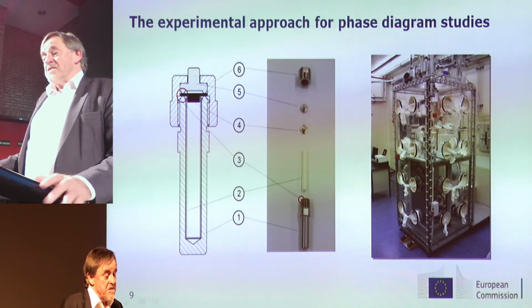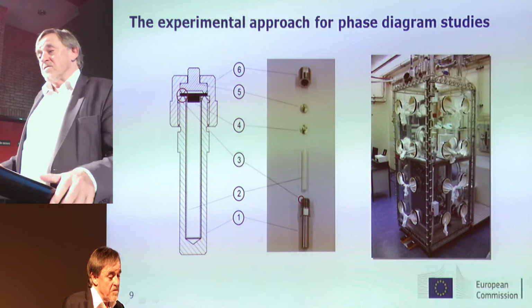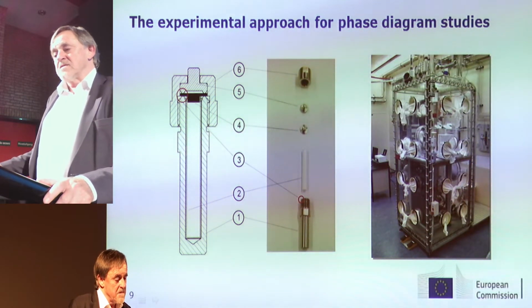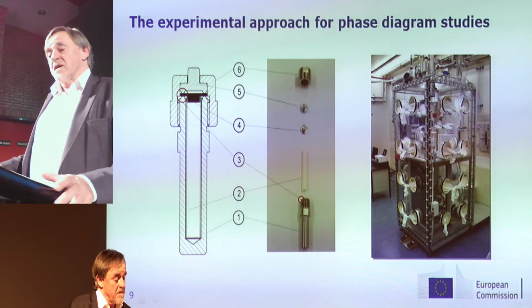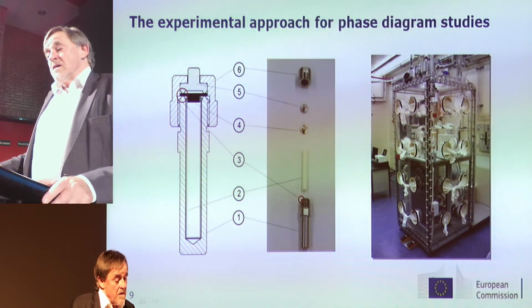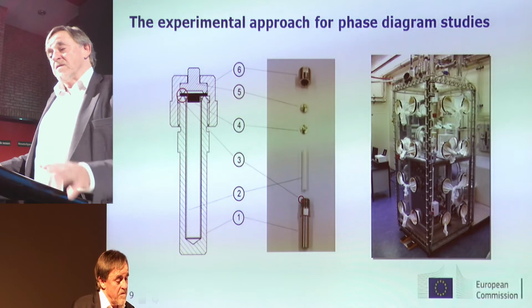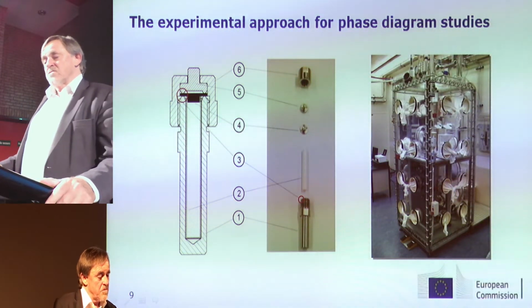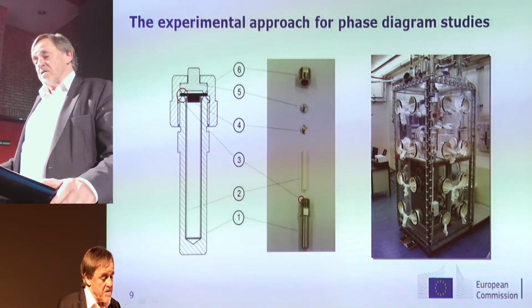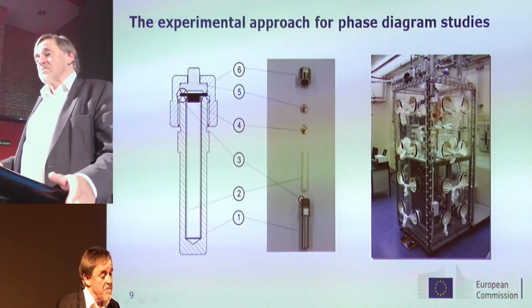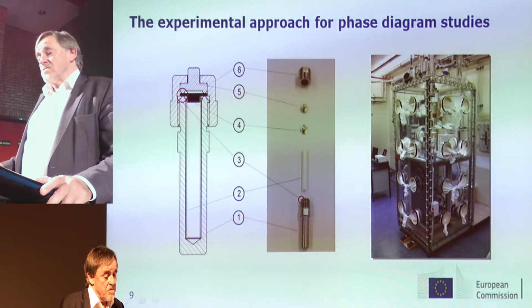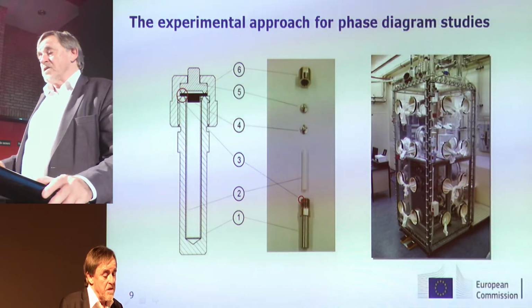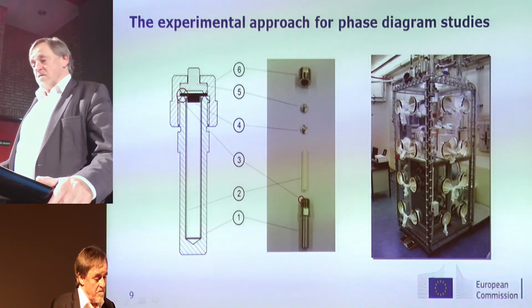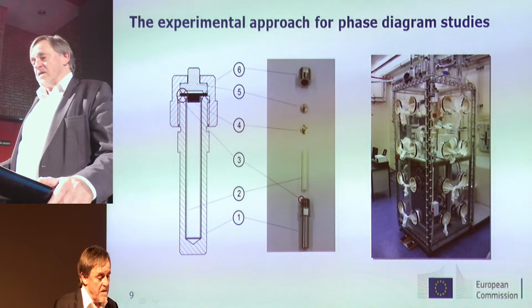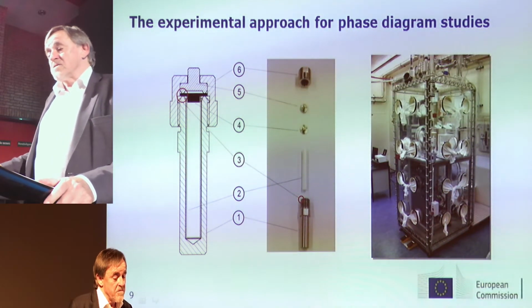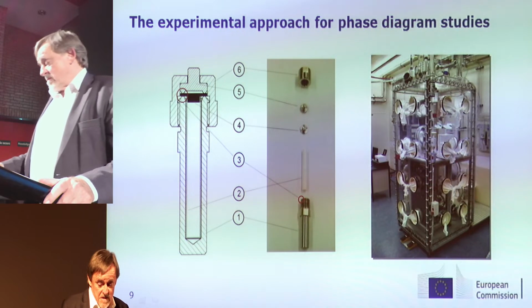Then our major tool that we use for the phase diagram studies is these special capsules with the boron nitride or nickel containers, which need to be completely sealed tight in order to, as I said, avoid vaporization. And all these activities are done also because we use, in addition to uranium, also plutonium. We need to work inside of a glove box, of course, where we have the differential calorimeter, which is used for these phase diagram studies.